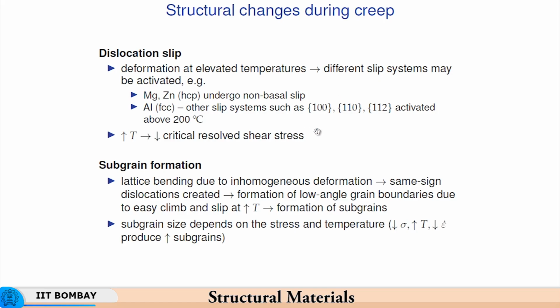We have seen that in crystal structures the close packed plane is the one that is a plane of easy slip. So, the 111 plane in FCC is the plane of easy slip, but then planes which are not favorably packed, in the sense they are not closely packed, also will become amenable to slip above a certain temperature. So, that is the reason why more and more slip systems come into play, and then the creep rate increases. So, one way to arrest creep is to make sure that the slip does not take place on these slip systems, and as the temperature increases, the critical resolved shear stress continues to decrease.